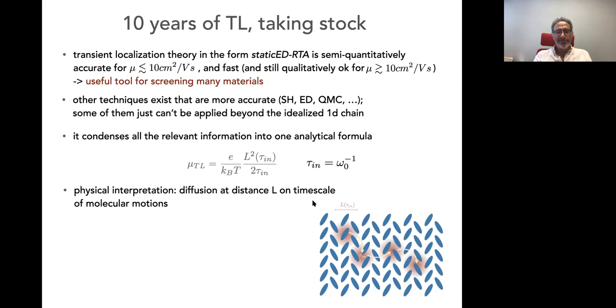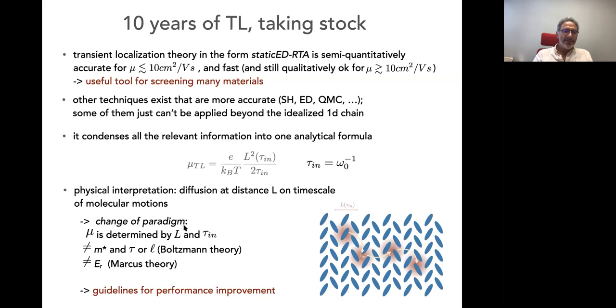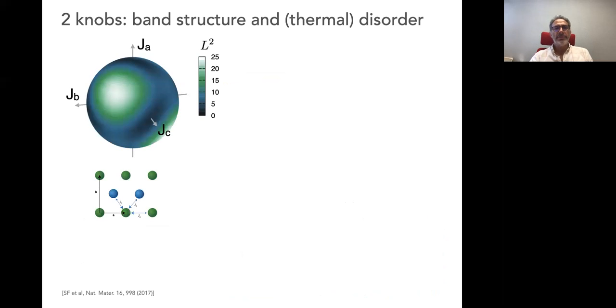So that's nice. But on deeper grounds, there is something here that is really a change of paradigm, because we are used to think of the relevant parameters being either effective mass and mean free path or activation energy. And here in this regime, it's really this localization length and this inelastic time that are governing transport. So this is very useful because it's really straightforward to at least try to give guidelines for improvement of performances. So we want to act on this length squared. So we have two knobs.